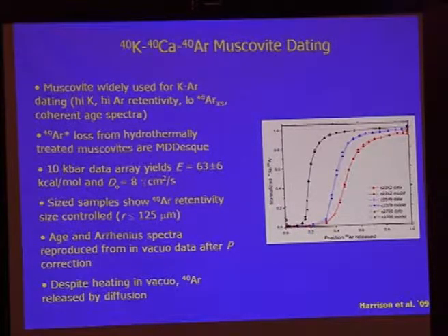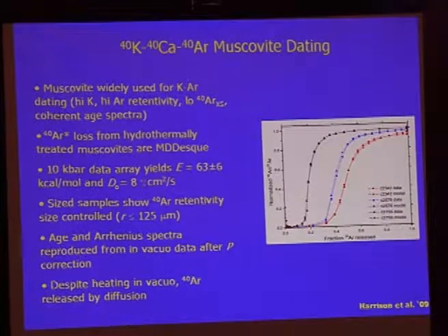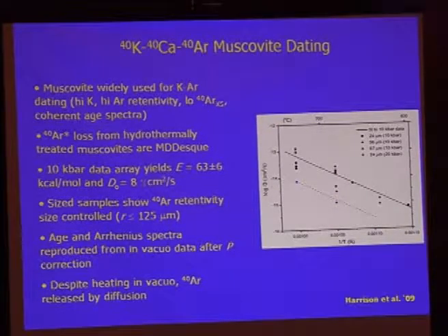It's a hydrous phase. Muscovite is kind of interesting. It actually dehydroxylates, but it produces a stable dehydroxylate form that, in fact, remains, or at least retains, the relative spatial position of the daughter product up to high temperature, above 1,000 degrees. So from this, we can calculate diffusion coefficients. So here's our Arrhenius relationship for 10 kilobars from these piston cylinder experiments.